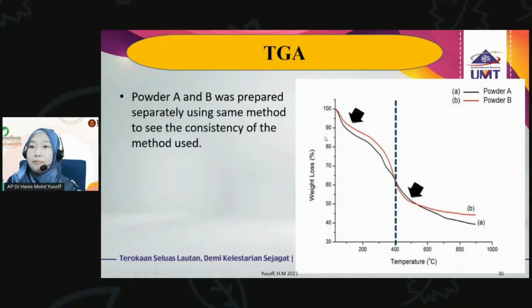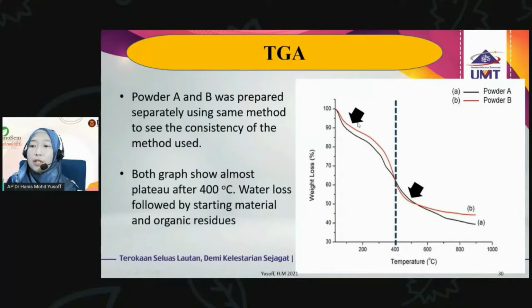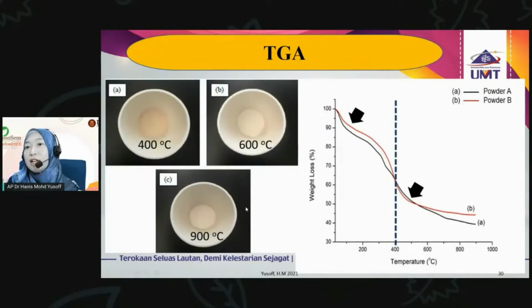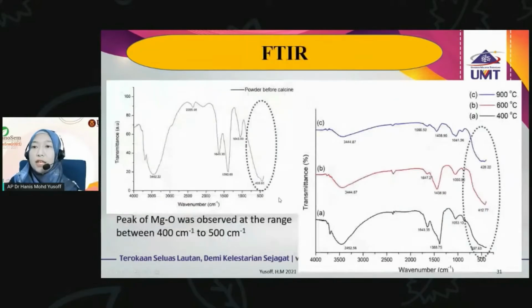So we assume that this is water loss and then the loss of starting material and other organic residue. So we choose the calcination temperature starting with 400, 600, and 900 degrees Celsius. And then, of course, the next characterization would be FTIR. So this is before calcination and after calcination.